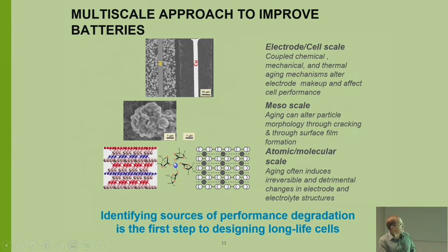And then there's the electrode cell scale. So that's where you're actually making the cell. So everything you see there is basically the electrode cell scale, and that's the level as an engineer where I work at. I work in this region. So we make electrodes, a positive electrode, so it's cathode particles on aluminum foil, both sides. This blank here is a separator, and then here's your copper foil, and that's graphite on both sides of that copper foil, and then they're wound or stacked together, and that gives you your full cell.